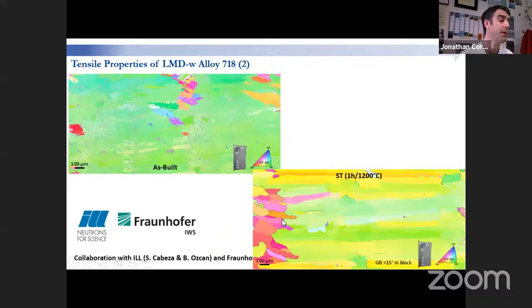Then we have been doing EBSD maps. That's a sketch of a wall from which we have been removing tensile specimens. Here you have an EBSD map in the as-built state and after solution treatment along the build direction, which is horizontal in that case. We can see that we have a very impressive texture in this material. We can recognize here one wire, another wire, and at each interlayer you have a little bit of recrystallization coming from the deposition of the N+1 wire.